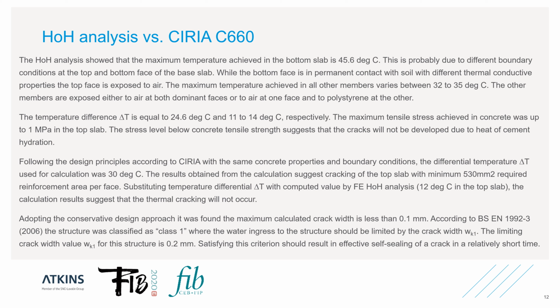The other members are exposed either to air at both dominant faces or to air at one face and to polystyrene at the other. The temperature difference delta T is equal to 24.6 degrees Celsius and 11 to 14 degrees respectively. The maximum tensile stress achieved in concrete was up to 1 megapascal located in the top slab. The stress level below concrete tensile strength suggests that the crack will not be developed due to heat of cement hydration.